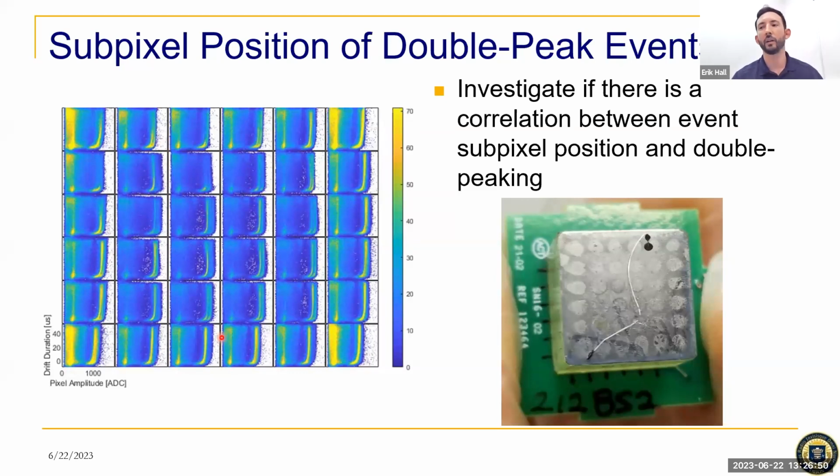And at the same time, when we take these crystals out of our readout system, we're seeing this pixel pattern develop on the cathode. So if the events are changing, that's making our photo peak wider and degrading our resolution.